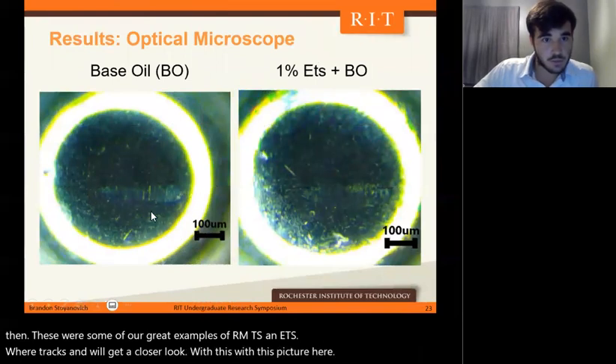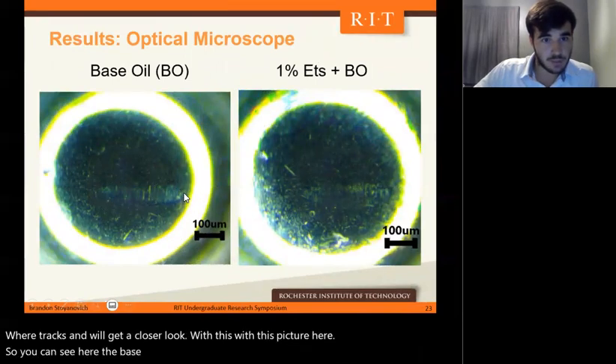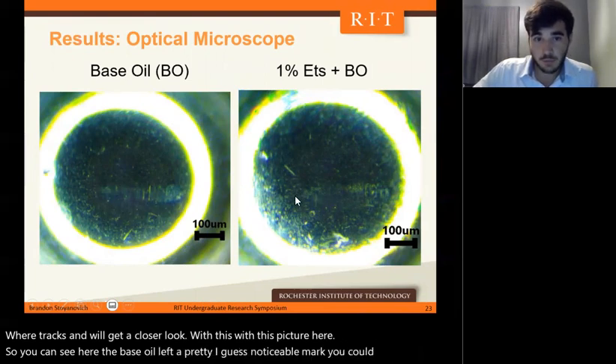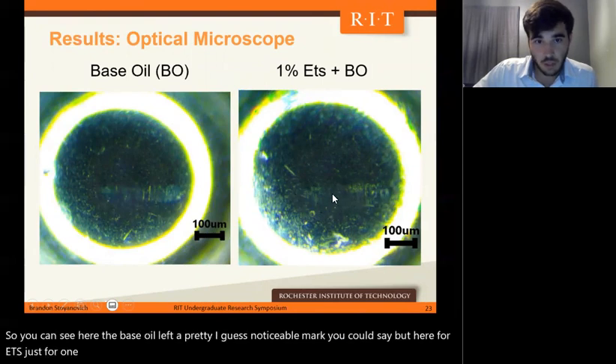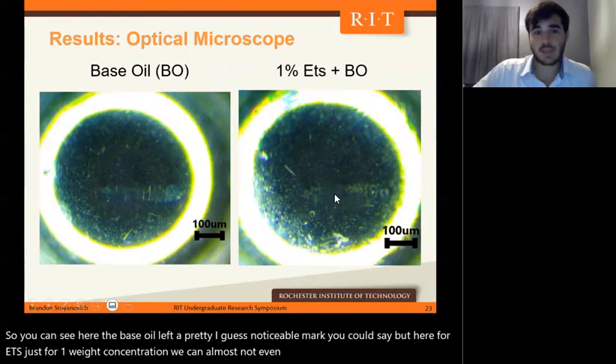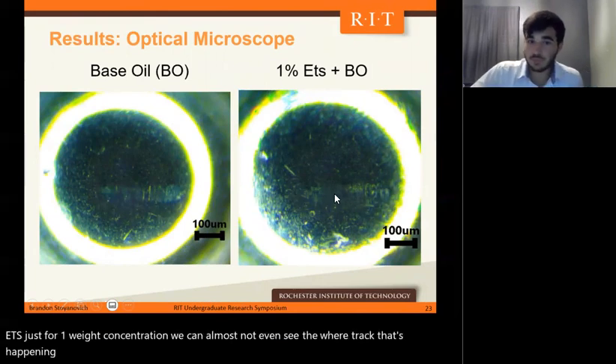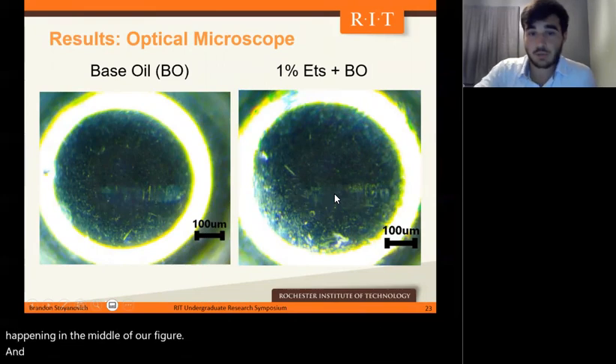So you can see here the base oil left a pretty noticeable mark. But here for our ETS, just our 1% weight concentration, we can almost not even see the wear track that's happening in the middle of our figure. And so that's a pretty astounding result. And this is just on the ball.